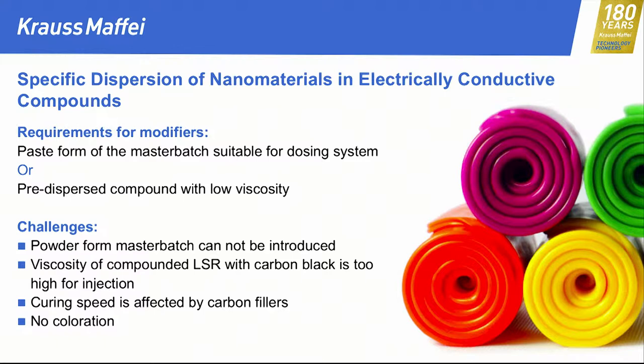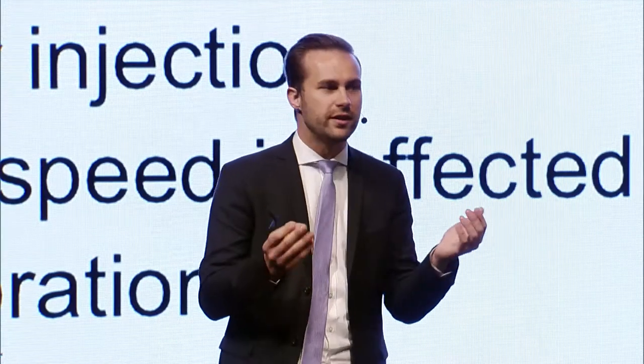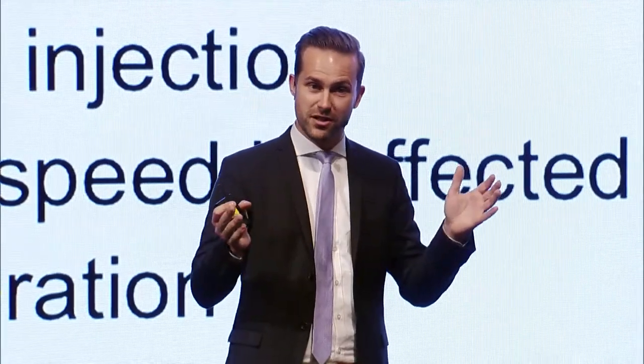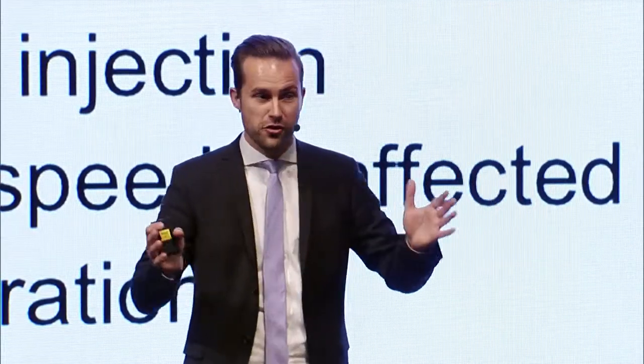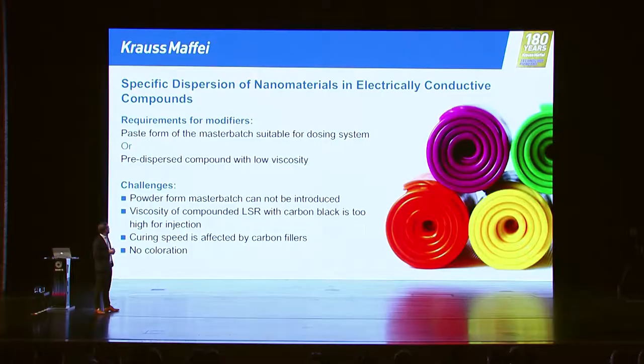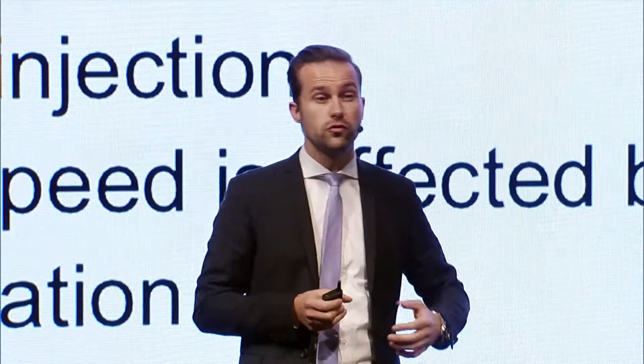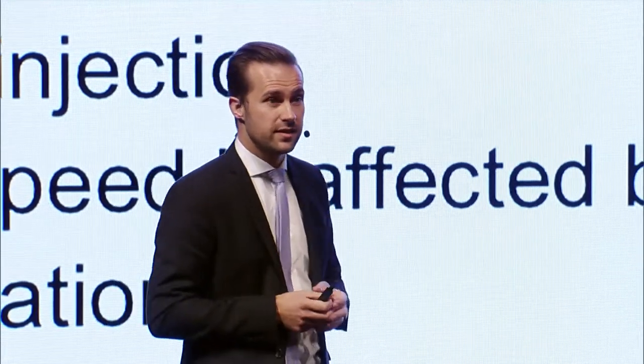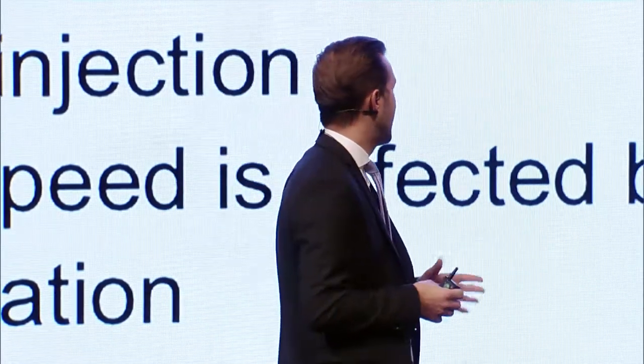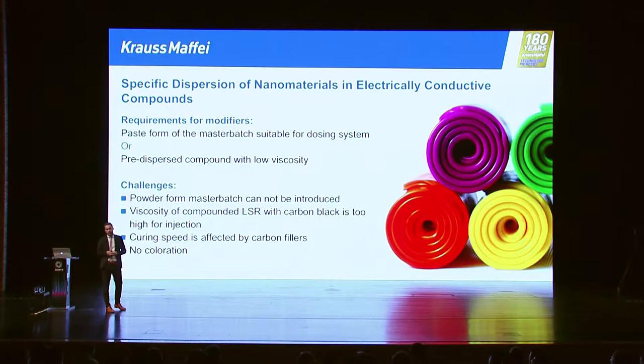nano-augmented materials. Normally, if you want to make a plastic material, this is what I learned in school and university, a plastic material has no conductivity. Of course, you can get conductivity as soon as you put some materials inside. But normally, you need a very, very high concentration of these materials. During compounding, you need like 10 to 40% of these materials inside your compound to be able to process it and to get a good electrical conductivity. So this is a huge challenge, and it's really a pain to process these materials due to the very, very high viscosity.